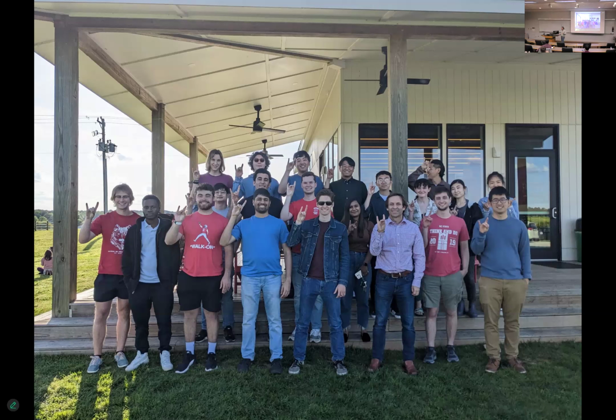However, gallium is much more reactive than indium. So its delta G of reaction is more negative. And so the oxide that you get is almost pure gallium oxide. So even though it's 25% indium, there's almost no indium. I mean, there's a little bit, but it's almost undetectable. And so your point is a good one.